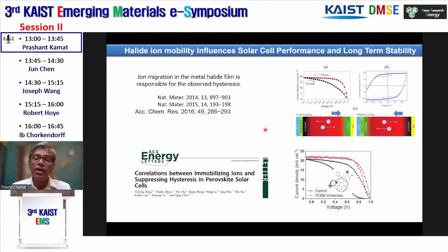That means when you are recording these JV curves, there is a reverse bias when you go in, and when you come back with a forward bias, there is a hysteresis. This was attributed to this ion accumulation at the electrode, creating a capacitance and then just being more resistive. However, people have found ways to make better cells and get rid of this hysteresis by adding different components or making a better electron transport and hole transport layer and other techniques.